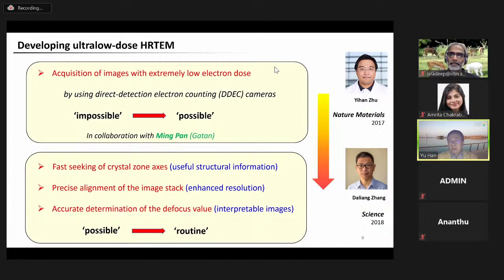So today, because the time is limited, I will make a long story short. Simply, we solve this problem in two steps. In the first step, we demonstrate that a new type of camera, called a direct detection electron counting camera, can form a useful image with the low dose conditions required by MOFs or other extremely beam sensitive materials, because this new type of camera is very sensitive.